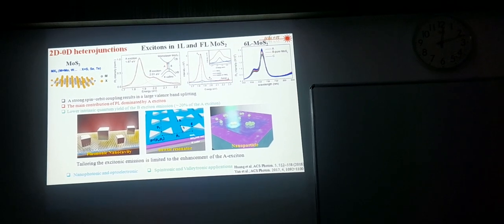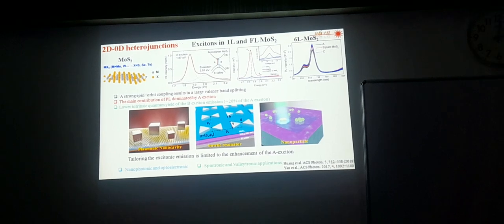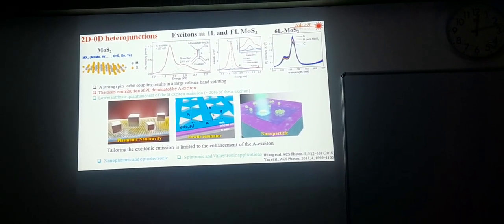And yeah, this I can skip for now. This is another 0D-2D heterostructure, based on molybdenum disulfide. Our motive was that this MoS2 has two bands, basically. The valence band has a splitting. If we consider two bands, A and B exciton, here you see the A and B exciton. Always this B exciton emission is suppressed because of the dominating A exciton. So the main aim was, if we can switch with electronic bias, this can be used to emit two different colors. So how do we do that?